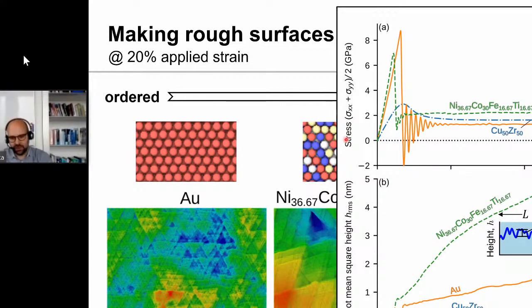While running these calculations, we can of course monitor stress and also the surface roughness. These plots show on the x-axis the applied strain in the system. The top one is a classical stress strain curve. Let me point out that there is an elastic regime, and then we have these huge stress overshoots for the crystalline systems because they are defect-free. This is sort of an artificial situation, but it's exactly what we wanted to test. And then these materials flow at almost constant stress as we continue to compress.